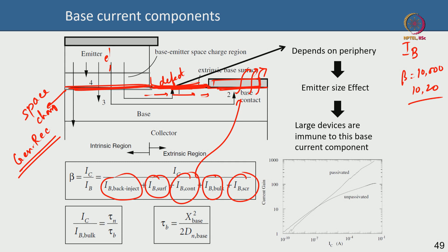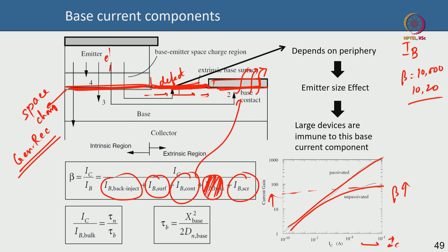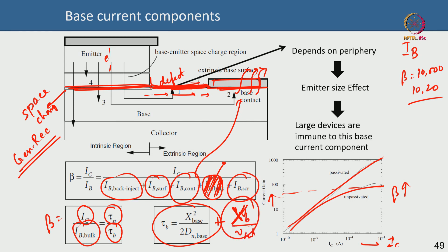Without passivation the current gain falls to around 10 or 20; with passivation it can reach 10,000. With higher collector current your beta goes up — that is the whole point. If bulk recombination is the major base current component, the current gain beta equals the minority carrier lifetime divided by the base transit time. The base transit time to first order is xB squared divided by 2D, and you also add xB divided by v_sat when dealing with highly scaled bases at really high frequencies.